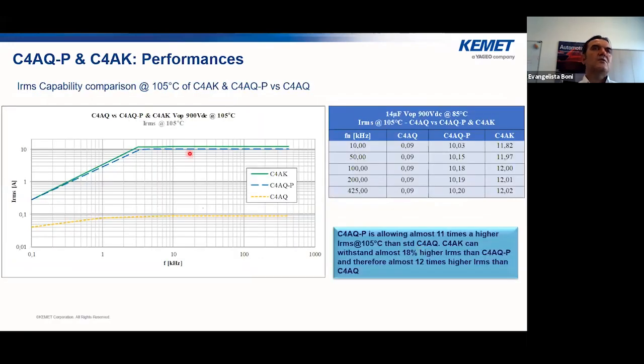And here we can see what we already saw for the resonant capacitor. This new series can work at higher temperature, and they can also offer the possibility to work at higher ripple current at higher temperature. In this case, it's possible to make a comparison at 105 degrees, where the C4AQP can have a current that is 11 times the standard C4AQ. And the C4AK is something like 18% higher than the C4AQP and 12 times higher than the standard C4AQ. And this is another example of power density, of the fact that this new series also meets the power density requirement.